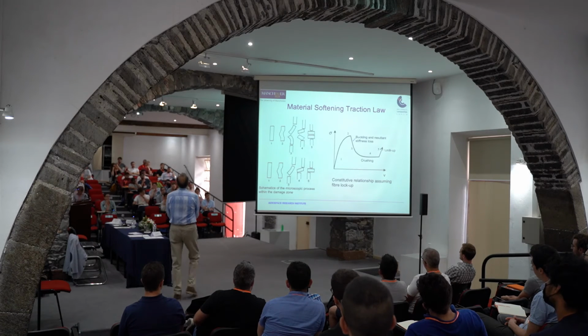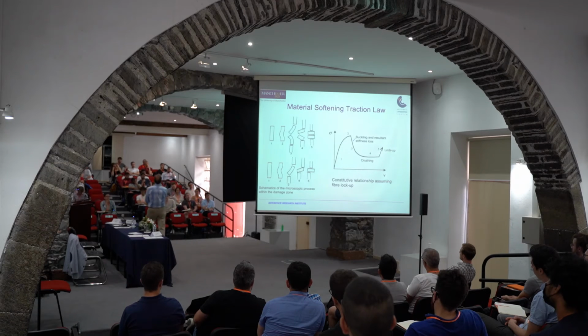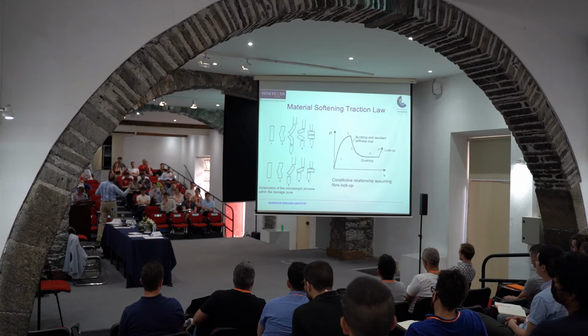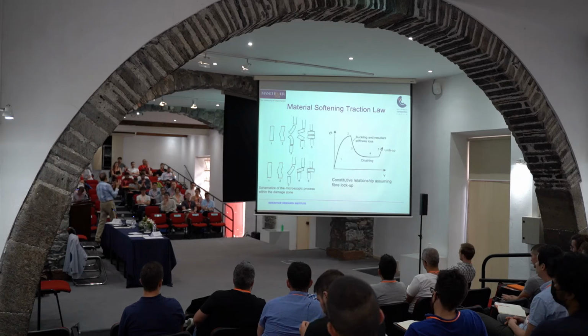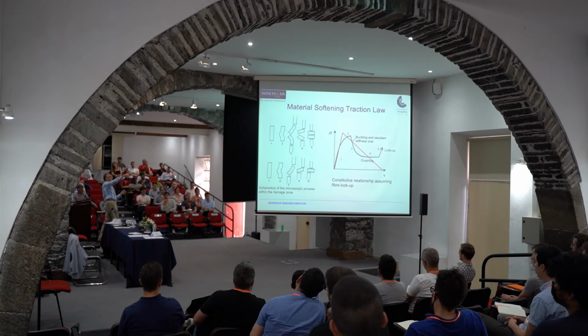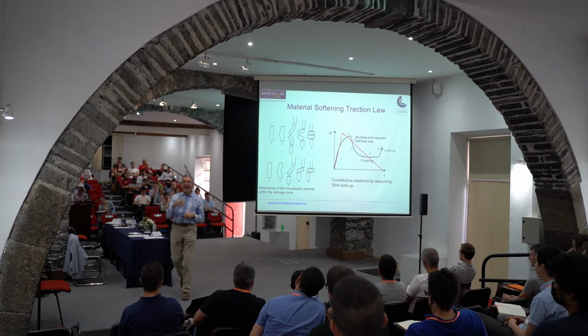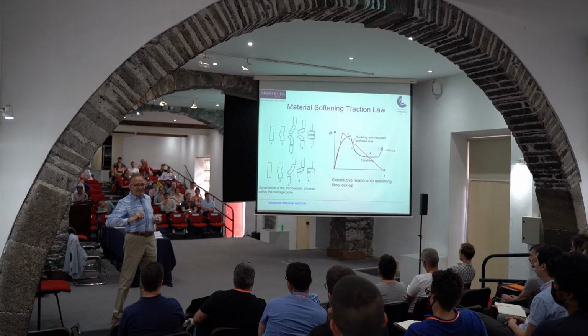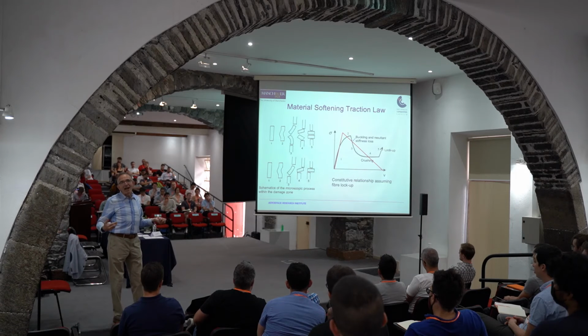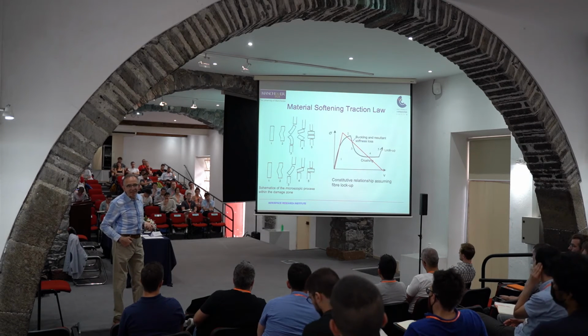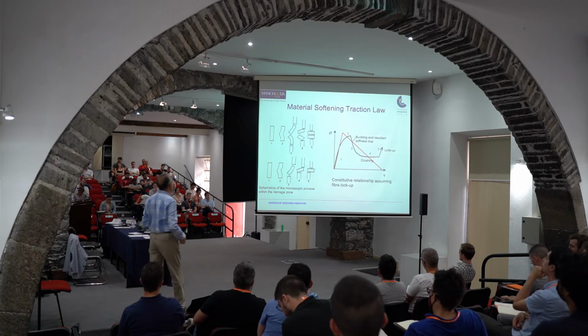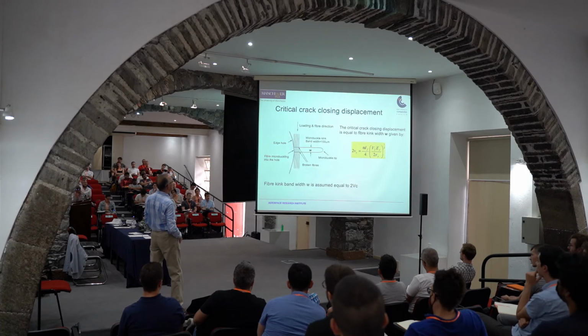Alright? But we know very well that those fragments actually do not lock, because the surrounding plies, in order to allow this rotation of the zero fibers, they have to delaminate. You see that in our X-ray CT. And since they delaminate, it means that those fragments follow, and they don't really do this local aspect. So it's useful mathematically for me to assume a linear reduction in that resistance that the buckled fibers provide, and see what kind of values I get for the overall compression strength and how it compares when Jack breaks those laminates and measures the strength.